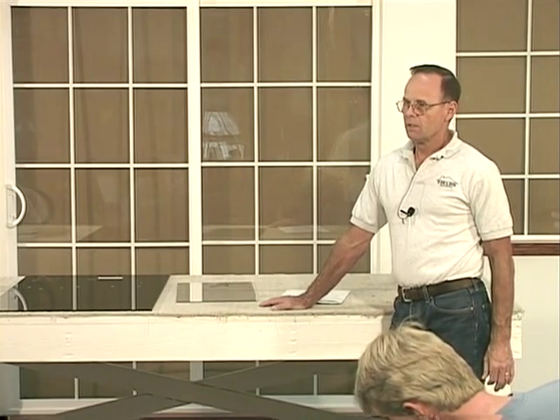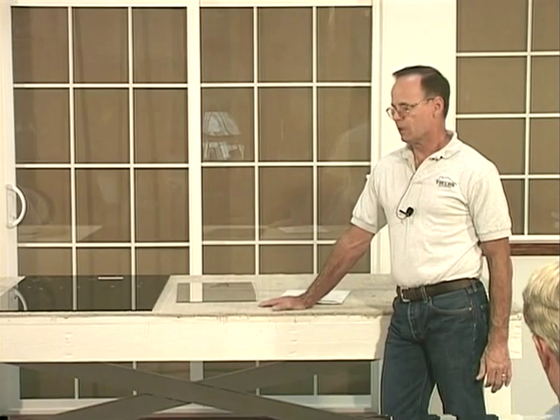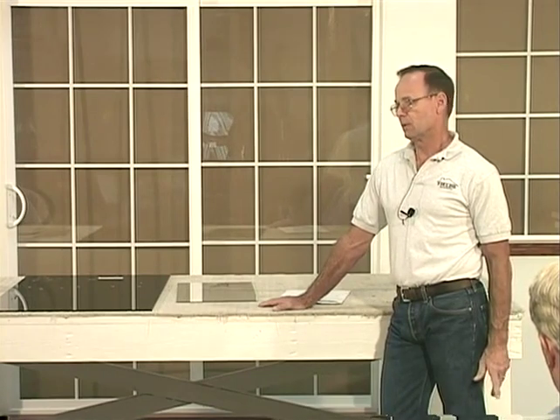That type of water spot is composed of silicate. The source of silicate on a lot of these water spots comes from two main areas. One area is building rundown off of precast concrete, which the silicate from the concrete does run down from the concrete onto the glass, dries on the glass, and actually attaches itself to the glass. The second source of the hard water spots is sprinkler systems. A lot of the sprinkler systems are being shot onto the windows, and sometimes there's silicate in it, sometimes there's magnesium or calcium, which usually doesn't present a problem.